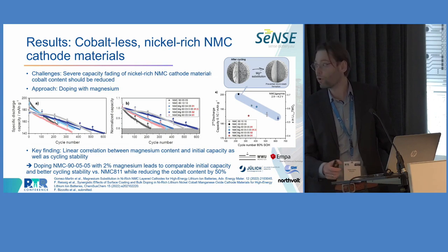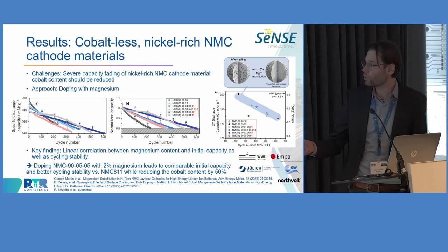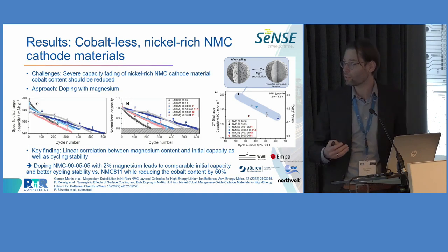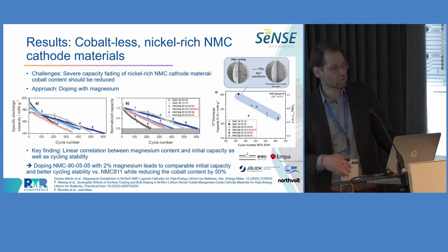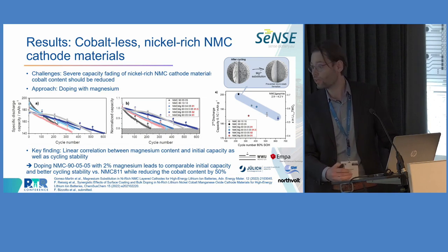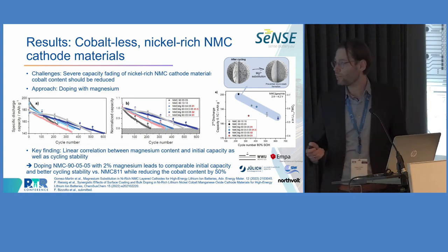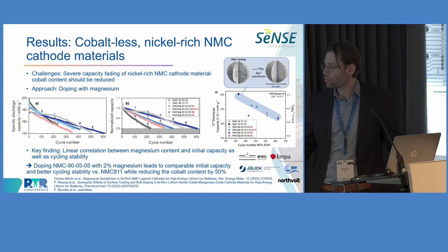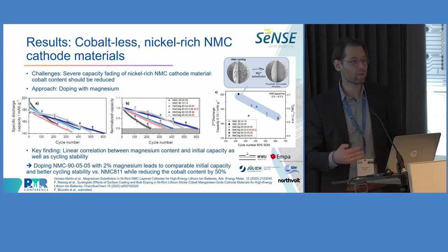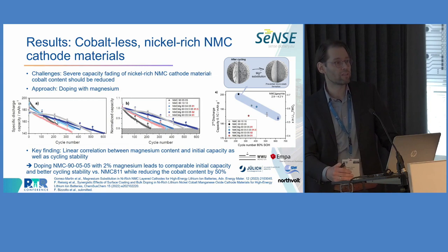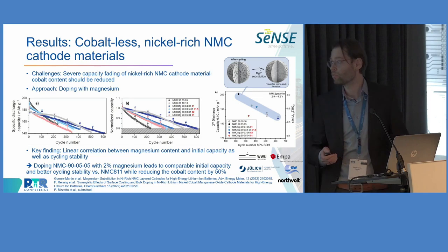For us, the starting point was NMC 811, so already quite a high nickel content. But then we wanted to go beyond also in order to decrease the cobalt content, which is one of these critical materials that was mentioned already earlier. So what we did here, and all these materials with these different compositions were synthesized with the same reactor. They all have similar properties in terms of particle size, in terms of morphology, in terms of surface area, which is important to be able to really compare the properties of these materials.